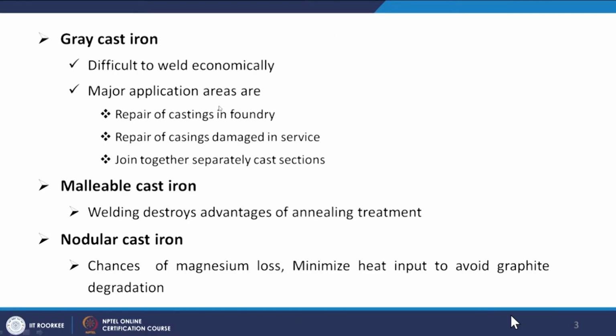Okay, so gray cast iron is difficult to weld economically. The major applications are repairing castings in the foundry, repairing cast damage in service, and joining together separately cast sections. Okay. Malleable cast iron welding destroys the advantage of the annealing treatment. And for nodular cast iron, welding changes the magnesium content through loss, and heat input should be minimized to avoid graphite degradation.